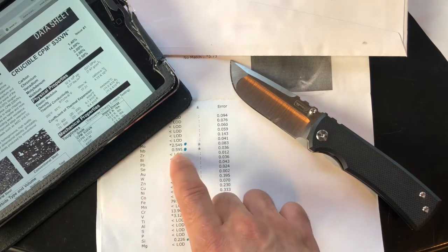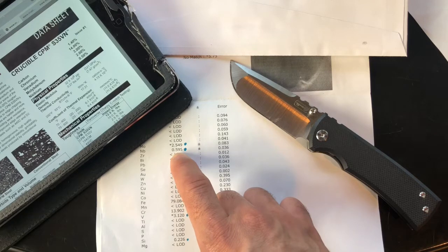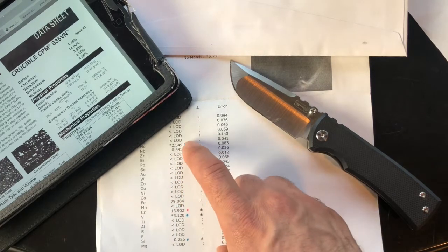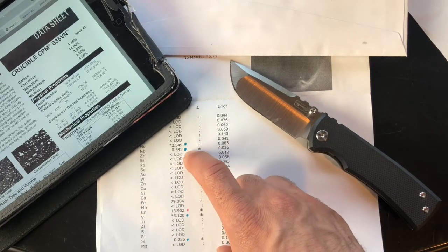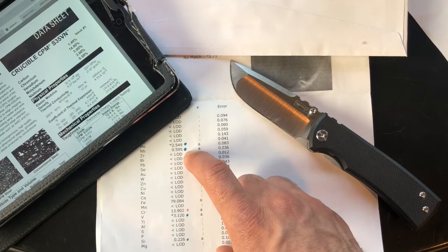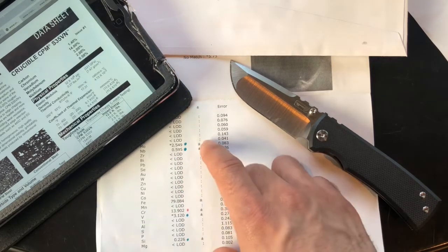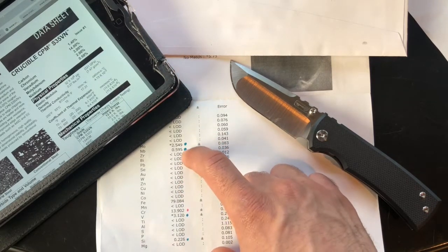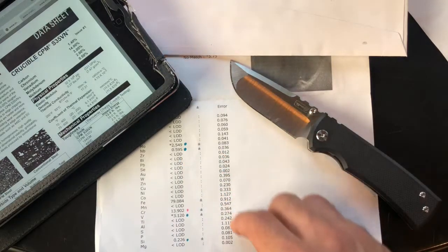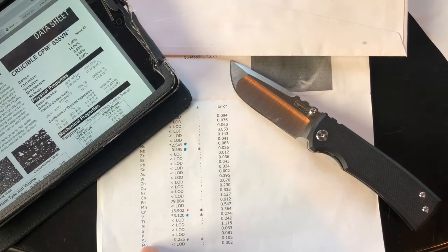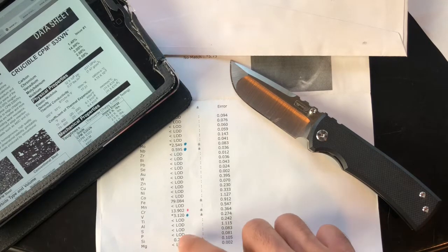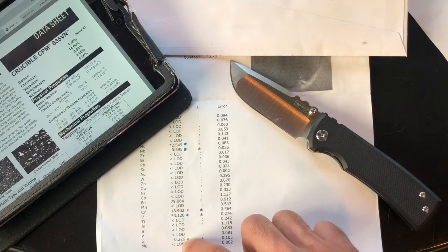And niobium, we're at about 0.595, which is a little bit more than what it calls for, which is 0.5%, half a percentage. And yeah, it's not bad to see. That's nice. The niobium is going to help it be stronger. We do have some silicon in here, which isn't exactly called for, but it's not that bad, and it's not a super high number either.